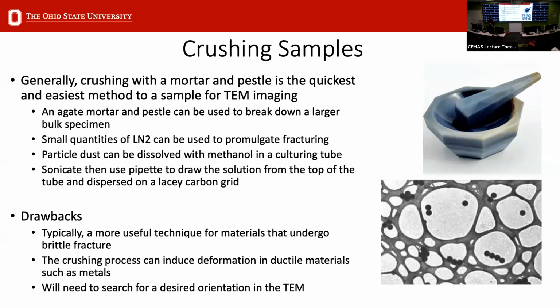So as I mentioned, if your materials are ductile or you care about observing deformation effects, you're definitely going to alter your sample by doing this. But the advantage is you can make your sample within an hour if it's applicable for you.